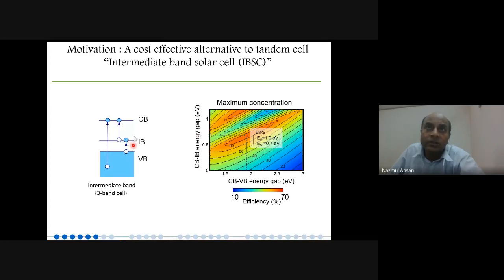So if you are switching the IB or changing the IB in between the gap, this is the idea here, that you are changing from 0 to some number. 0 means your IB overlaps with the conduction band, and if you increase more and more, you are increasing the gap and putting the IB closer to the valence band, and this goes down there, and you make the combinations of all these band gaps and do the thermodynamic calculation, and you put them in this color map. Then this blue area tells 10% solar cell conversion efficiency.